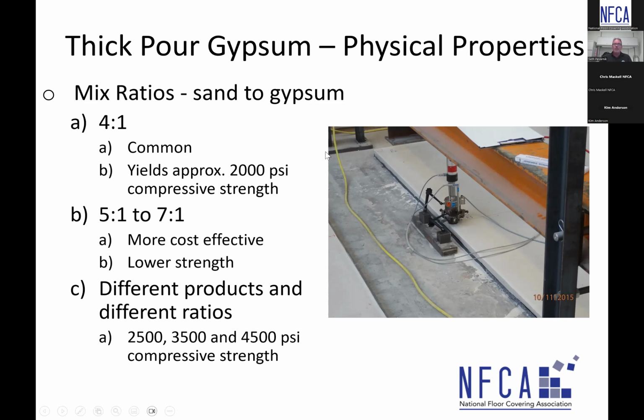So back to the physical properties of the gypsum, the 4-to-1 ratio, 4 parts sand, 1 part gypsum, when mixed with the correct amount of water at that correct ratio, very commonly yields a 2,000 pound compressive strength value. Certainly if they're doing a 5-to-1, 6-to-1, 7-to-1, which tends to be more cost effective because the sand is less expensive, the end result may be lower strength values.